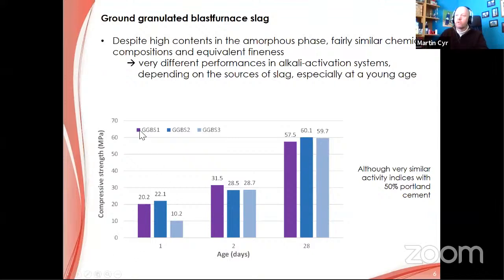You can see here three commercially available GGBS in Western Europe. Even if we achieve almost the same compressive strength at 28 days for the concrete, we can have very big differences at young age. And it is often a problem when you have to design for industrial projects, you have to design your material and you see such a difference.